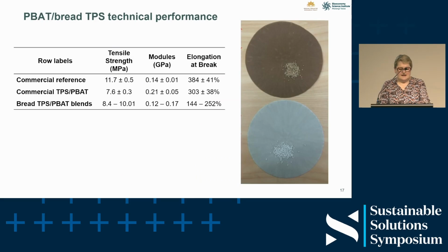Then we had to look at the technical performance to work out whether or not we could potentially turn this into bread bags. The top numbers relate to the commercial reference product, which was supplied by Convex. We don't actually know what copolymers or plasticizers were put in that, but it's commercially available, and it has a tensile strength of about 11.7. This should be the modulus, the middle one, that measures the flexibility, of 0.14, and the elongation at break is quite long. Then commercial thermoplastic starch made with the native wheat extract and PBAT came in with a lower tensile strength, but elongation was still quite good. And the bread one looks sort of in the range, but a little bit lower.